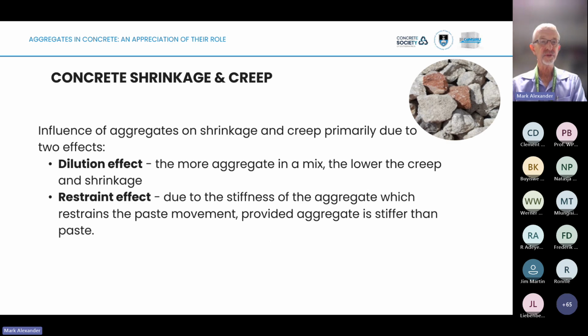Now, talking about shrinkage and creep, two important properties of concrete. Aggregates affect, as we saw right from the very beginning, they affect this very profoundly. And there are two effects. It was what we call the dilution effect, which is simply the figure that we saw earlier. I'll show it again now. And the restraint effect, which is due to the stiffness of the aggregate.